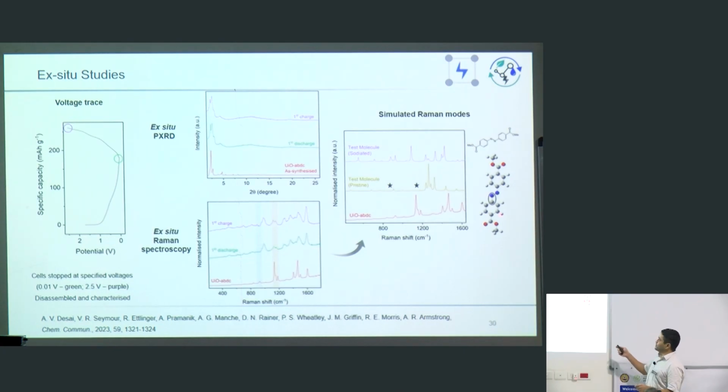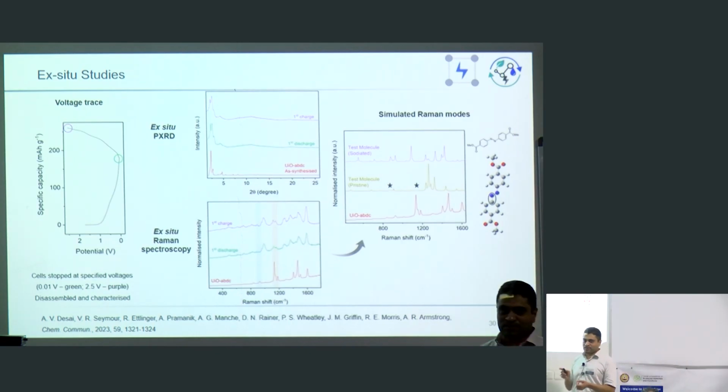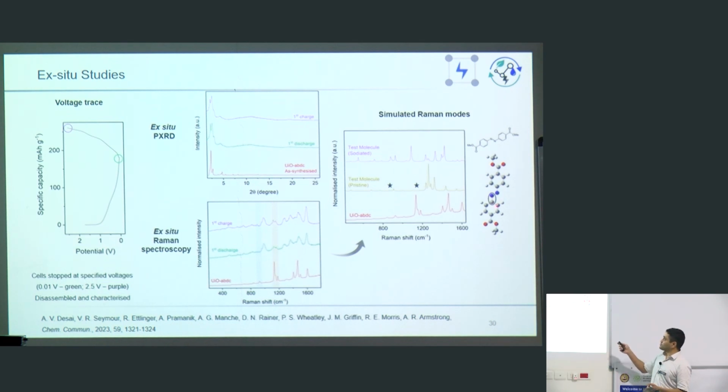In this particular case, this band, which is the C-N stretching, appears in the same region as these peaks. The idea is that if your azo group is participating in the redox activity, the sodium is going to sit next to this azo group, and it's going to block or reduce the intensity of this stretching. The peak associated with this stretching is now going to minimize.